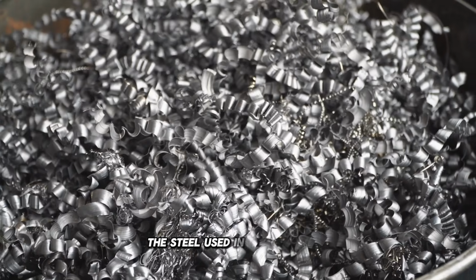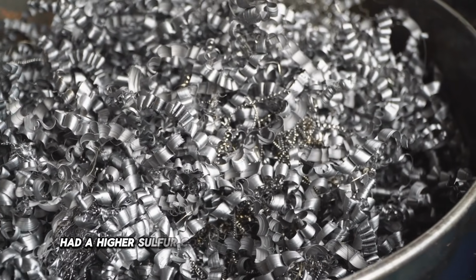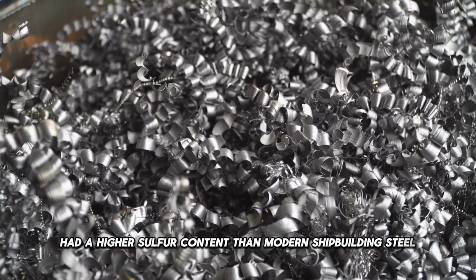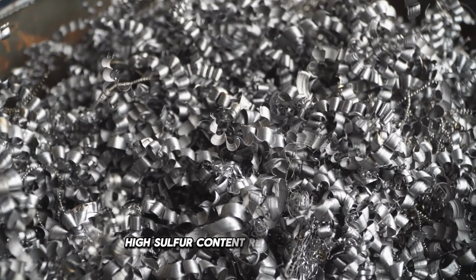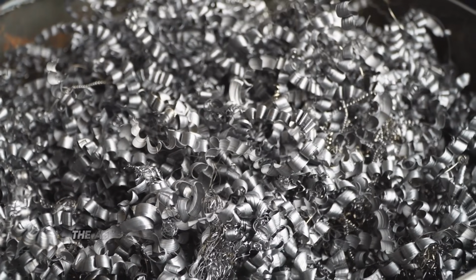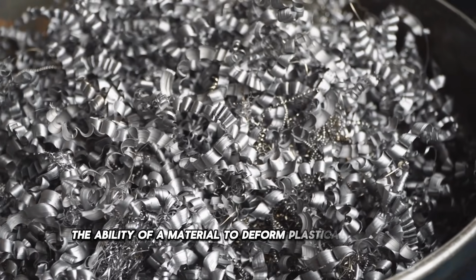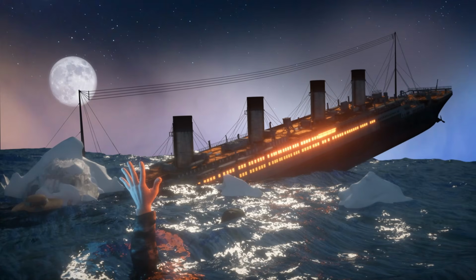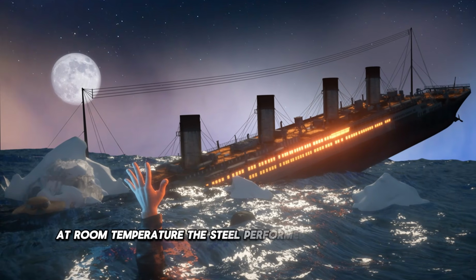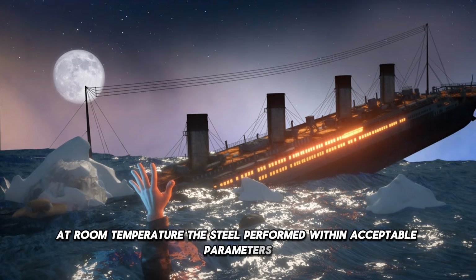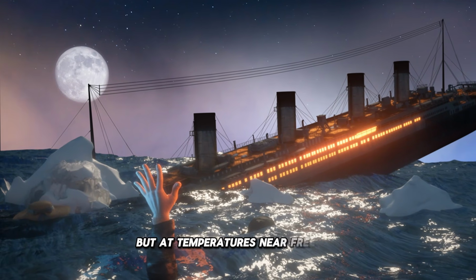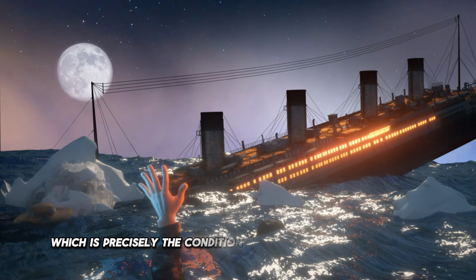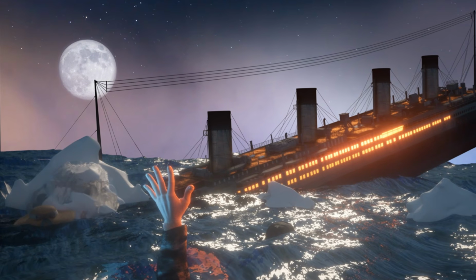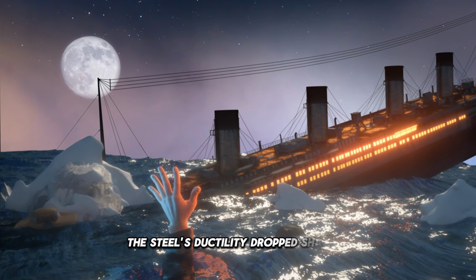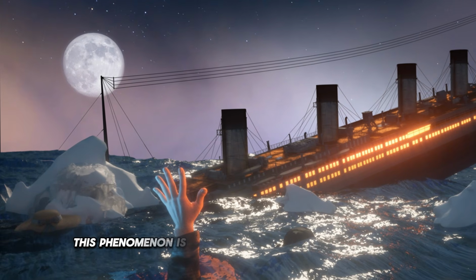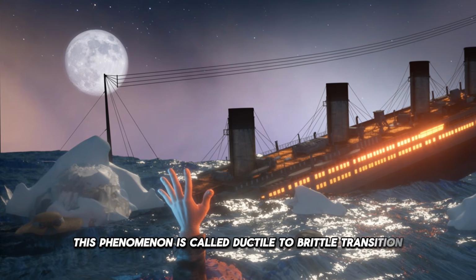The steel used in Titanic's hull had a higher sulfur content than modern shipbuilding steel. High sulfur content reduces ductility, the ability of a material to deform plastically before fracturing. At room temperature, the steel performed within acceptable parameters. But at temperatures near freezing, which is precisely the condition of the North Atlantic in April, the steel's ductility dropped sharply. This phenomenon is called ductile to brittle transition.